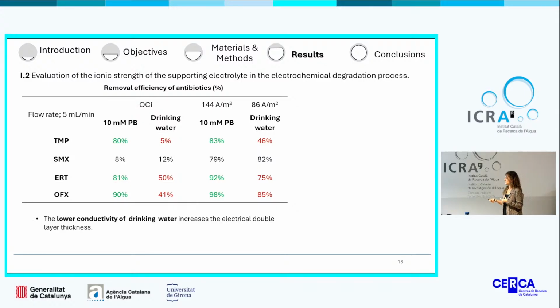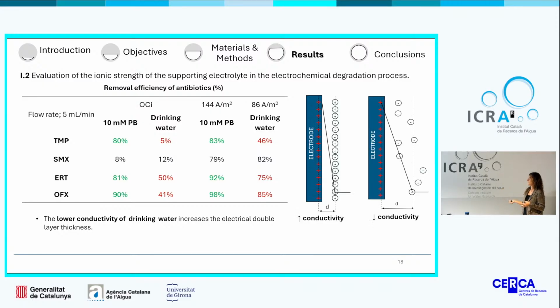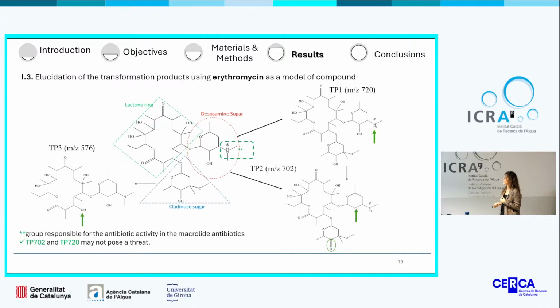And this is probably a consequence of the lower conductivity of drinking water, which increases the electrical double layer thickness and avoids the direct contact or somehow limits the interaction between the antibiotics and the electrode. However, when the application of current was induced into the treatment, more than 70% removal was achieved, except for the case of trimethoprim.